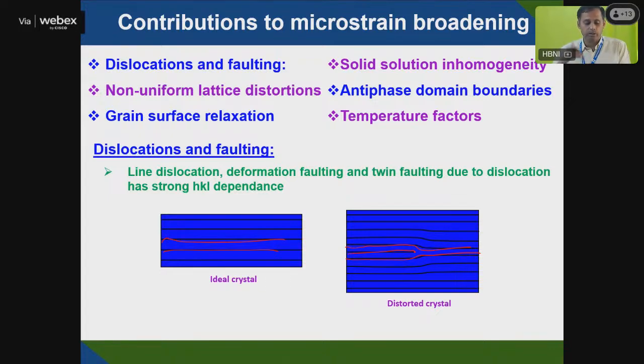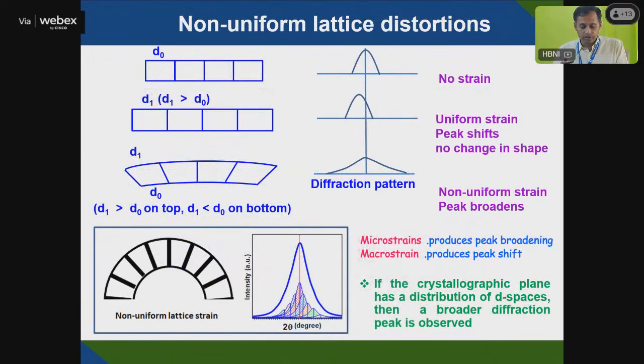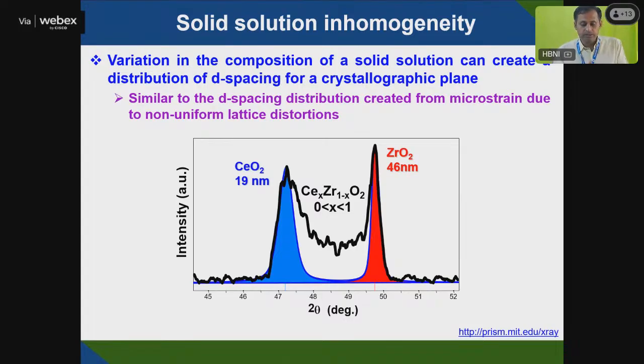So those types of information you can also get from diffraction, whether there is grain surface relaxation or solid solution inhomogeneity. I have given one example here. You can see the solid solution, if I take cerium oxide and zirconium oxide, my cerium will give this blue peak and zirconia will give my red peak. When you make a solid solution, like I prepared cerium zirconium oxide, Ce x Zr 1 minus x O2, you will get a peak like this, the black one. So you have to identify the solid solution homogeneity or solution limit by using this X-ray diffraction method.